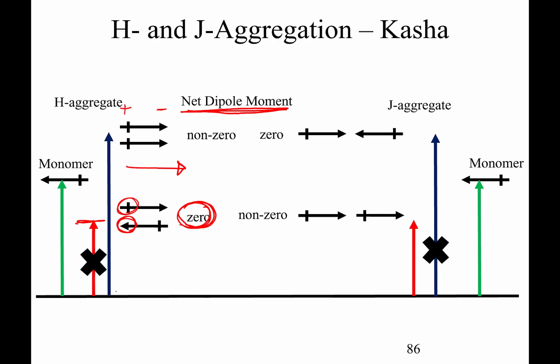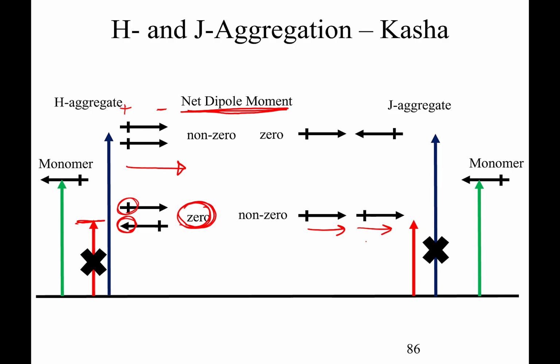aggregate, they basically have this head to tail geometry in the ground state or in the lower state, and in this particular case we sum these transition dipole moments up. It's a low energy state because we have the minus here that's right next to the plus, so that is an attractive situation. So we do have absorbance to the lower energy state for a J aggregate, but when we have the high energy states, we've got a negative here and a negative here. They repel each other. Of course, we've also got a net zero transition dipole moment. So this absorbance is not allowed.